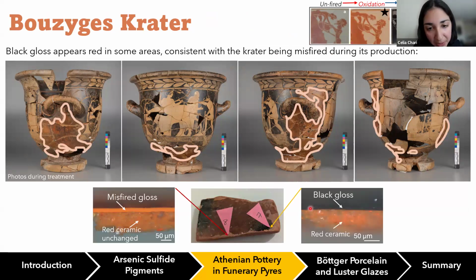And instead of it being a layer of gloss trapping black particles, it seems to have trapped red particles instead. This is something that occurs during misfiring, so during the actual production of the crater. And this can be supported by the idea that we're seeing this throughout the crater. It's not just in some small sections that seem to be defined by the break lines. Instead, we see it all over the crater's body.